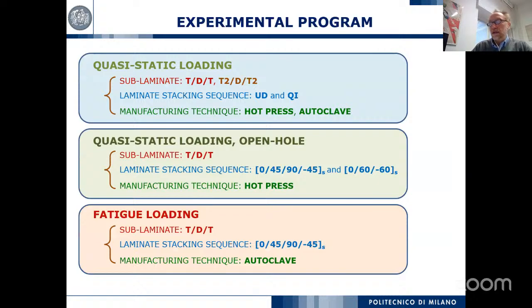So moving to the mechanical behavior. We investigated the quasi-static loading for all laminates and all sublaminates, and the two manufacturing processes. We also included the open hole test to assess the notch sensitivity, and then finally the fatigue loading. Obviously, at the beginning we tested all the laminates I mentioned, and then moving to open hole and fatigue, we reduced the number of materials and laminates because of the material we had available at that time.